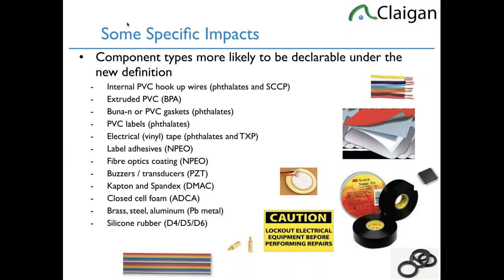But it's only on average. They only control the chlorinated paraffin by chlorine content. They have every kind of paraffin you can think of in there. And CP52 is usually 20% SCCPs, and that's why it turns up. So we tested on the open market over five countries, 253 flexible PVC samples. 29% failed for SCCPs. Every single one of them would be a recall issue.